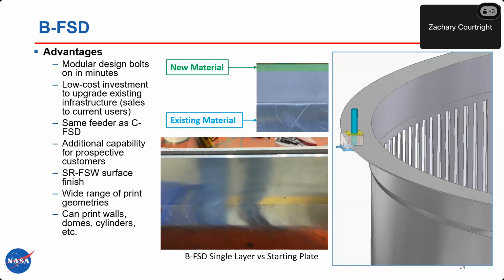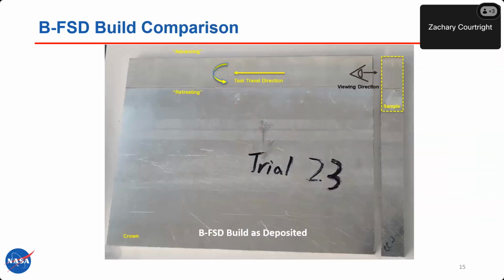surface. And then there's a couple images, like this image in the center here shows a plate before pass and after pass. So you can see that's a plate that hasn't been deposited onto next to a plate that has. So you can see the 1/8 inch difference in height with a single pass. Next slide, please. And then, yeah, so we took one of these, and this one is as built.